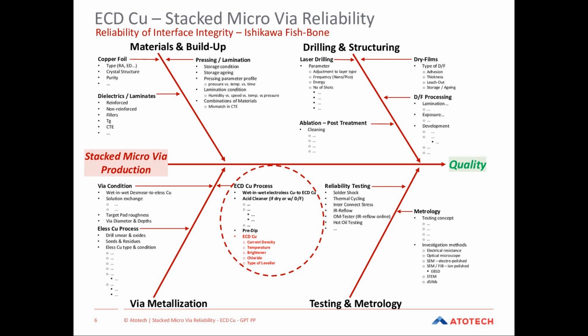We look at all parameters of the plating process, and we found that the current density, the temperature, and so on are also very important parameters you can adjust and modify in production. At least you have some possibilities to optimize here, and often these parameters already give you a strong improvement already.